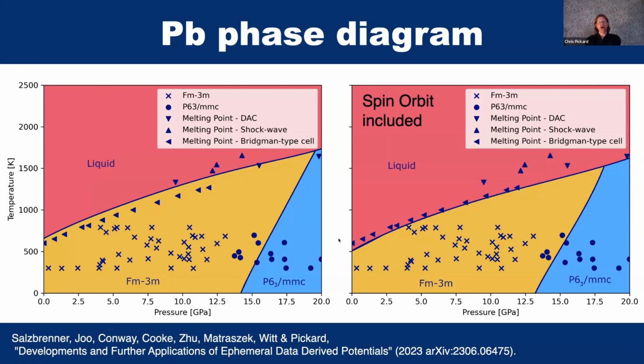His task had been to bring temperature into random structure searching. And so he's used these potentials to map out a phase diagram of lead. Now, lead is quite difficult to do from first principles. It's a metal, so the Brillouin zone needs to be very carefully sampled. It's also very heavy, so really you should include spin orbit interactions, which makes your DFT calculations expensive. In order to map the melting line of lead, in principle, you need to calculate coexistence molecular dynamics.